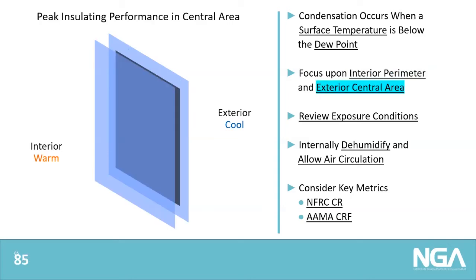And likewise, in terms of the heat escaping to the outside, there's less heat escaping to the outside at the middle of the panel relative to the perimeter. So at the perimeter, we may have effectively a heat trace, whereas in the middle of the panel, there's not heat transferring, so the exterior surface could remain below the dew point.